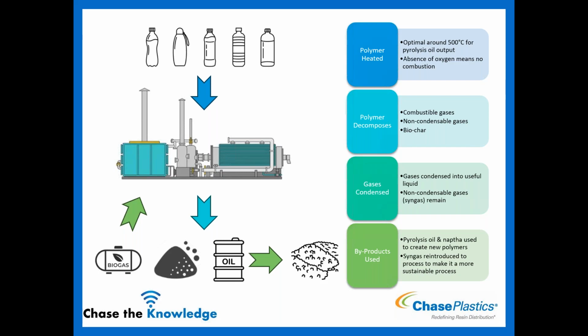So that's what most companies tend to run it at. You also, when this is done, it's in the absence of oxygen, so there's no combusting. So the combustible gases, which are a product of this after the polymer decomposes, they don't combust and start to blow up. So there's no oxygen, so it allows that to happen. So the creation after the polymer decomposes is combustible gases, non-condensable gases, and then biochar are created. So it's going to be kind of your three little pictures down here showing that.